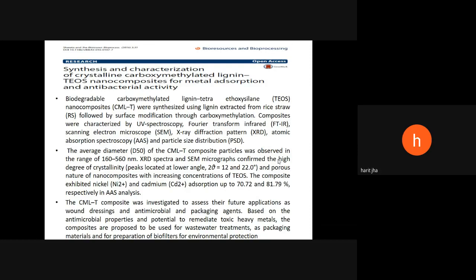The average diameter of this composite was between 160 to 560 nanometer. The XRD and SEM confirm the high degree of crystallinity and porous nature of the nanocomposites with increasing concentration of TEOS. The composite exhibited 70 to 82% removal or absorption of the nickel and cadmium. It was also further investigated to assess their future application as wound dressing and antimicrobial and packaging material. Based on antimicrobial and potential to remediate toxic heavy metal, the composites were proposed to be used for wastewater treatment, as packaging material, and for preparation of biofilters.